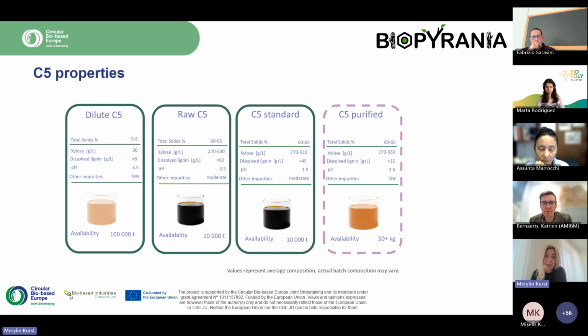For the C5 stream, the process begins with a dilute solution. After the evaporation step, a concentrated raw C5 stream is obtained. That means before entering the lignin sedimentation tank. And this raw C5 contains up to 60 grams per liter of dissolved lignin. Following lignin removal in the sedimentation tank, we get the standard C5 product, and it has a reduced lignin concentration of below 45 grams per liter. Further purification yields a purified C5 stream with lignin levels below 15 grams per liter.